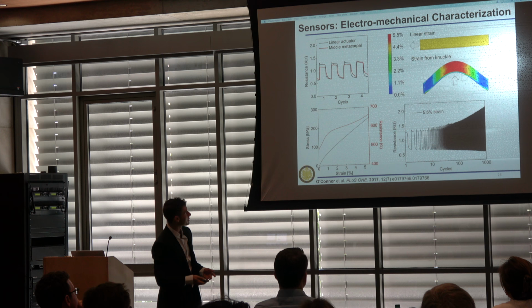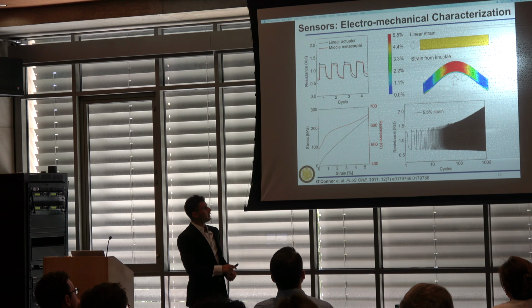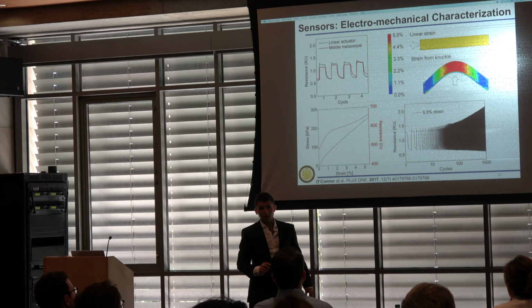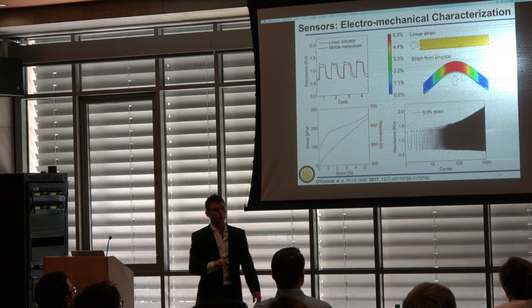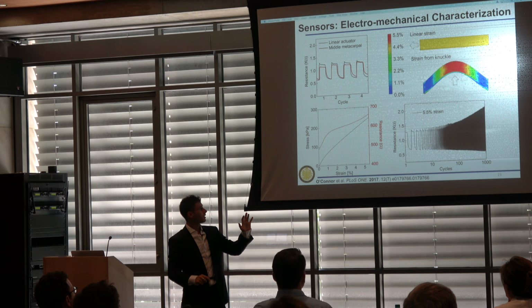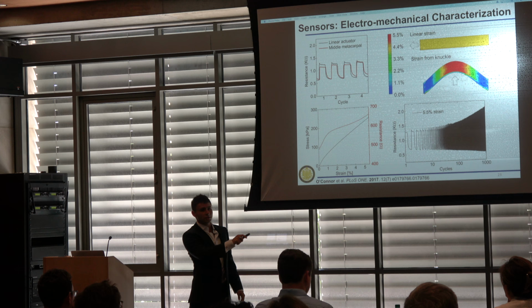And what we find is after 1,000 cycles, so this is a log plot, the signal does change after many hundreds of cycles. The high bound increases, but its ability to detect whether the knuckle would be bent or relaxed, whether the fingers were articulated or not, would still be preserved. Actually, the sensors would just become more sensitive. And since in this application in particular, we're just looking for the change of state from low to high,